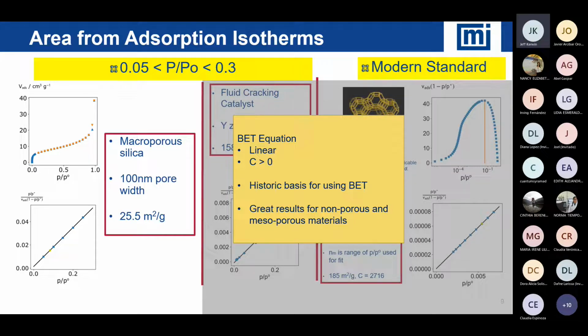Now, historically, where it has been great and people have always trusted it and used it is if we have a material that's non-porous or mesoporous. So I've got fairly large size pores, 2 nanometers up to 50 nanometers, or non-porous, BET surface area is very, very effective. And we only need 2 simple rules. We only need to make sure that when we apply the BET equation, it's linear, and that when we look at the intercept and we calculate the BET constant, the BET constant is greater than 0. So 2 very simple rules for applying BET surface area.